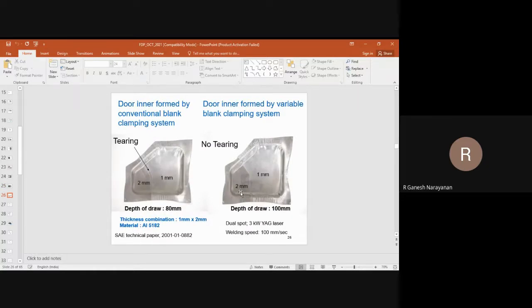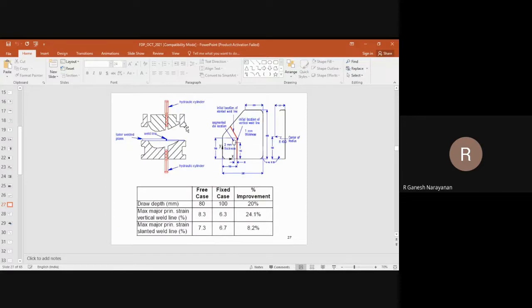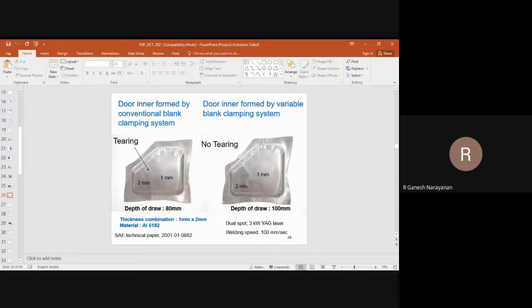This is another example where you can see a variable blank clamping system. What they have done is, I will show you a schematic here. See, this is a component they make, and this component fails in this corner. Okay, this is made of aluminum material, 5 series, 1 mm on one side, 2 mm on the other side. Okay, and when you do normal forming deep draw, the depth of draw is 80 mm only, and it fails here. And the weld line slightly moves also. But when they have done a differential clamping mechanism or variable clamping mechanism, they made a 100 mm draw and there is no failure. Okay, what is that variable clamping mechanism? What they have done is they have used a hydraulic cylinder to clamp the sheet closer to the weld, closer to this corner specifically, so that the material movement is actually manipulated, such that you avoid this necking.